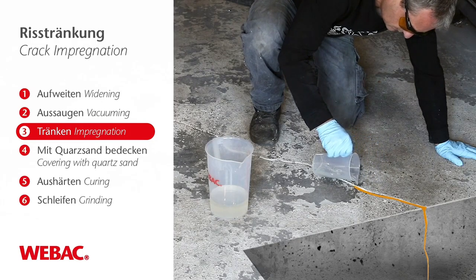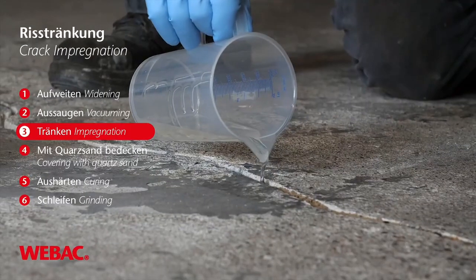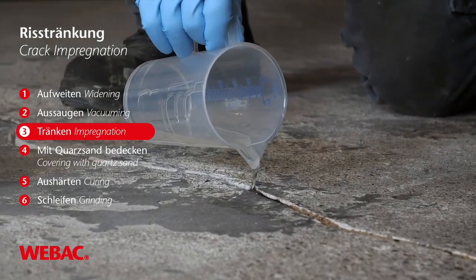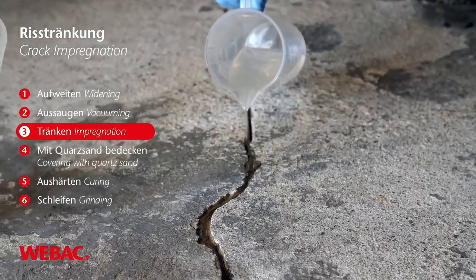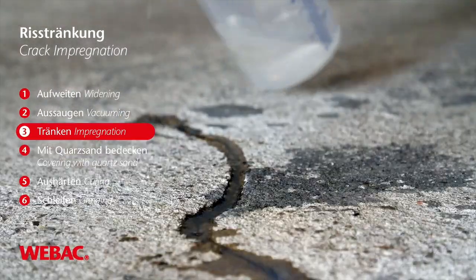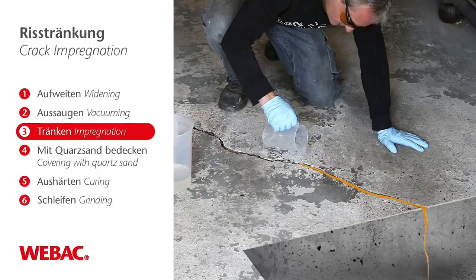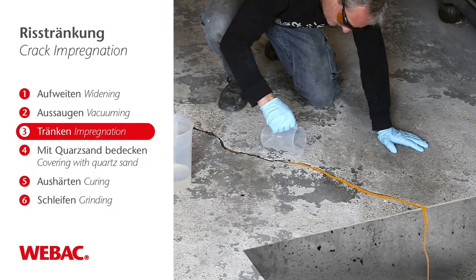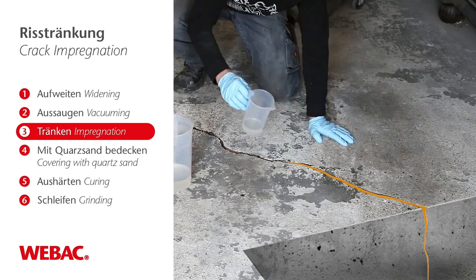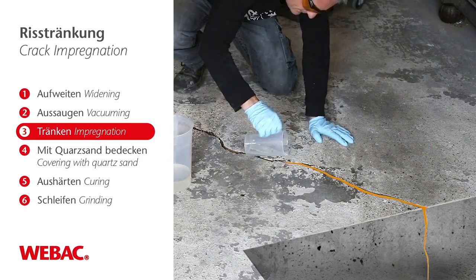This step has to be done a couple of times, because for sure the injection material is going to penetrate into the concrete, find fissures, cavities and so on. So material is gone and you have to repeat the step of filling until the crack is filled up to the surface.